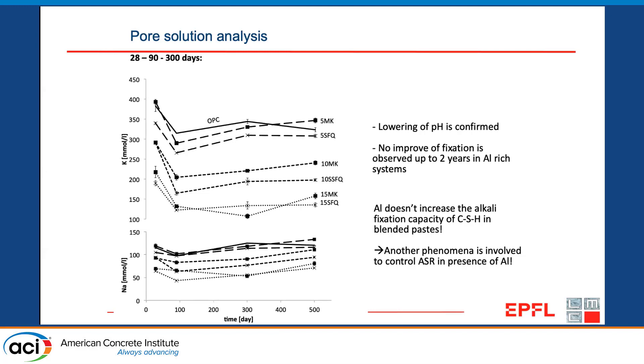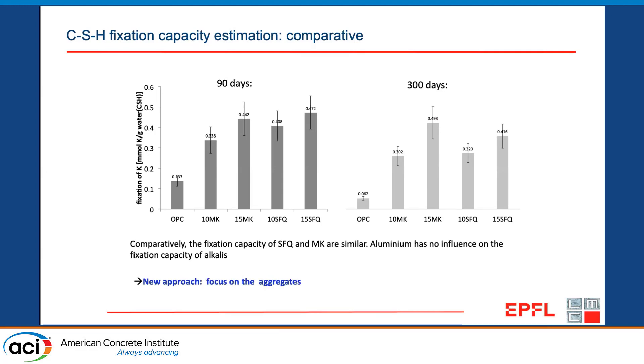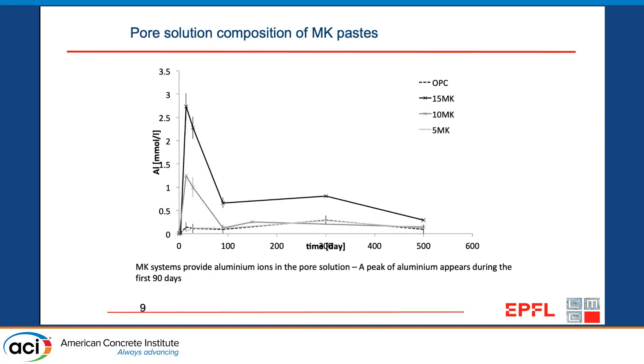When we expressed the pore solutions, we found that the hypothesis wasn't true. Here is the alkalinity of the pore solutions — at five percent silica fume with quartz, and five percent metakaolin — and in each set you can see the alkalinity in the metakaolin cases is actually slightly higher than in the silica fume cases. Our analysis showed that if anything, the metakaolin is fixing less alkali than the silica fume, so the hypothesis in the literature didn't really fit the facts.